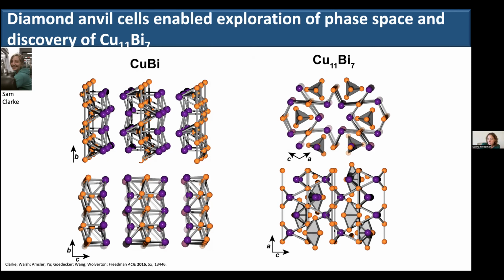So we have these 2 compounds, and not only were we able to synthesize them in a diamond anvil cell, we were also able to access these materials in a multi-anvil press. So I've literally held both of these compounds in a gloved hand, and they persist to over 100 Celsius in a DSC experiment.